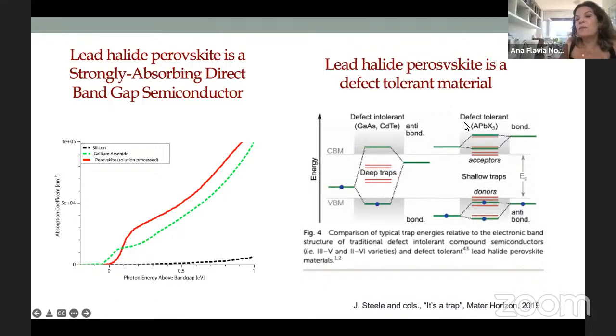In the case of the metal-halide perovskites, you can see here that the traps are shallow. It means that the energy levels of these traps are very close to the valence band, or even to the conduction band. So imagine an electron trapped in this acceptor, very close to the conduction band. Any thermal energy can just make this electron jump back to the conduction band. That's what we call a very defect-tolerant material.